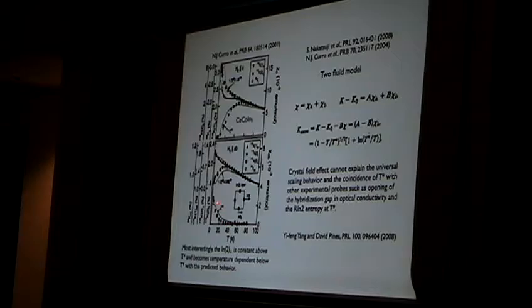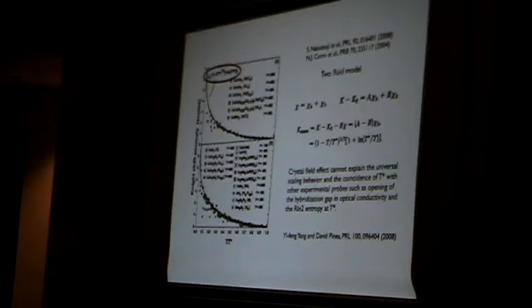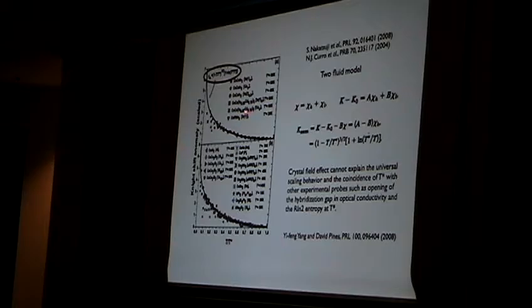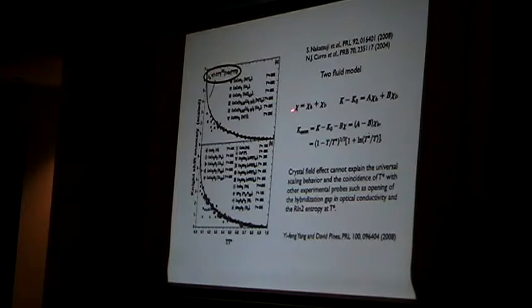The interesting thing is for this indium-1 site, it's constant at high temperature, which suggests that A_d is zero, that the local moment hyperfine coupling is zero. So it directly probes the heavy fluid. In fact, it does probe the heavy fluid, and this curve as well as many other Knight shift anomalies in many other materials does follow the formula with the same universal behavior. The original theory explained this Knight shift anomaly by crystal field effects, but crystal field effects can't give such universal behavior.